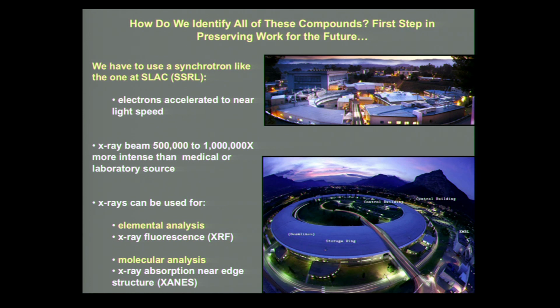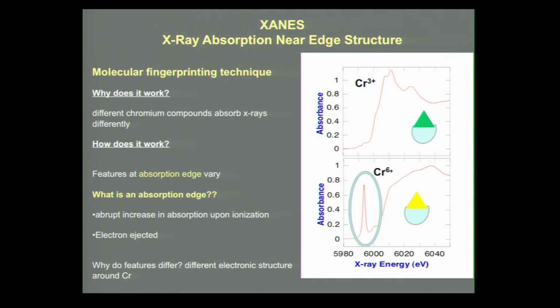And the reason that we like these very intense X-ray beams so much for studying art is that they give us elemental analysis information using a technique called X-ray fluorescence, and they also give us molecular analysis information using a technique called X-ray absorption near edge structure. And so these are two of the synchrotrons that we used in our research, the one here at SLAC and then also one in Grenoble in the south of France. So this is X-ray absorption near edge structure that was used to study the Van Gogh, and essentially it's a molecular fingerprinting technique. In terms of why it works, different chromium compounds are going to absorb X-rays differently, and we can use that feature in order to identify them.